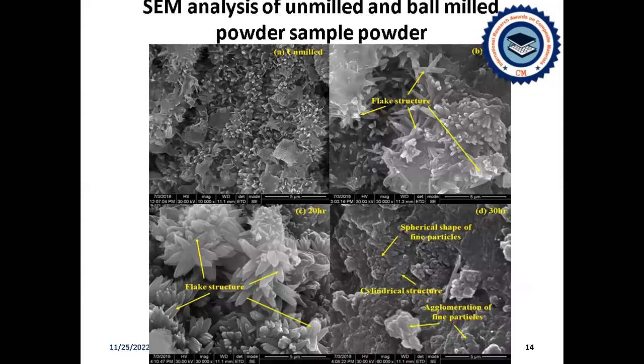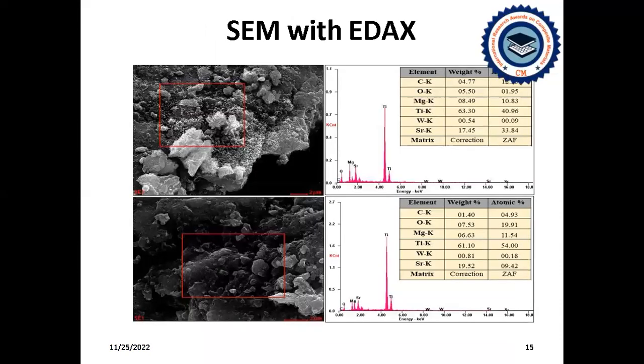And this is the SEM analysis of the unmilled and ball milled powder samples. It represents the unmilled powder sample where the powders are seen, and as the milling progresses up to 10, 20, and 30 hours, the micrographs show the flake structure of the powder particles and the agglomeration of the powder particles, and the cylindrical structure and spherical shape of the fine powder particles due to the cycle of fracturing, cold welding, and flattening of the powder particles.